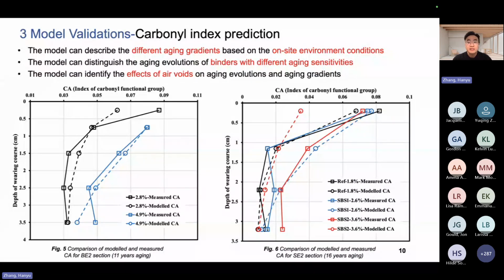What we see here, the model can distinguish the aging evolutions of binders with different aging sensitivities. Then if we look at the left figure, we use the same binder, but the cores, the different parts where we drilled the cores, have different air voids. And what we see here for the left figure, the model can identify the effects of air voids on aging evolutions and aging gradients. So we are not going to perfectly match the measurements because it's almost impossible. But the model is useful if it can have the three features as shown in this slide.